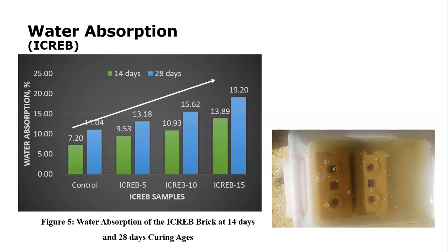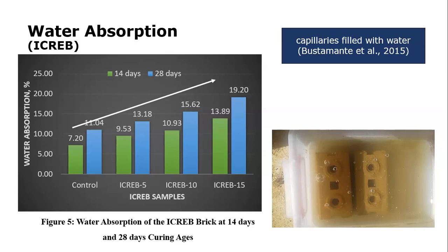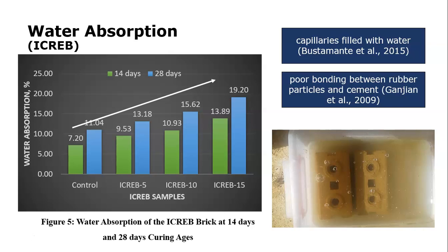So these results indicate that the composite brick containing a higher percentage of crumb rubber will absorb more water during wet curing or hydration process. And the reason for this behavior is possibly due to the existence of capillaries in bricks which are filled with water. In addition, poor bonding between rubber particles and cement paste also causes the rubber-cement interface to pressure the water to flow around the concrete matrix. So that's why the water absorption increases as the amount of rubber in the bricks increases.